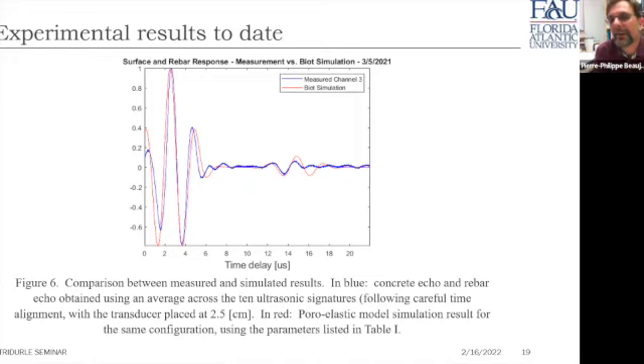So it is not about a spatial resolution as it is a change in the spectrum of the echo, which back in time is translated into a sequence of a surface echo and a rebar echo separated by not only a very specific time, but the shape and amplitude. So to answer your question, we do not actually look at the very specific time alignment of echoes to create an image of what's happening in the concrete as it is traditionally done.